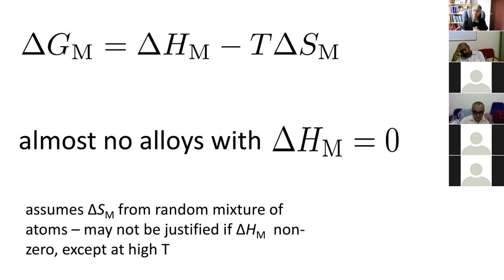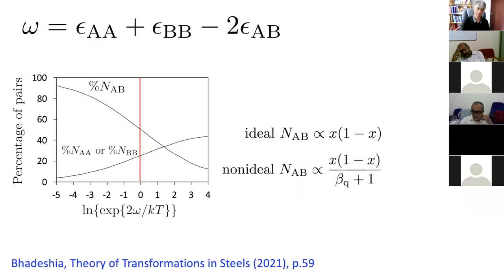But it's possible, using thermodynamics, to actually allow for a finite enthalpy of mixing and a non-ideal entropy of mixing. And I gave a set of lectures at IIT Kharagpur, which are on my YouTube channel, which discuss the quasi-chemical model, where we have a finite enthalpy of mixing and a non-ideal entropy of mixing. Therefore, I'm not going to go into any detail, but just to show you the outcome in a binary case,